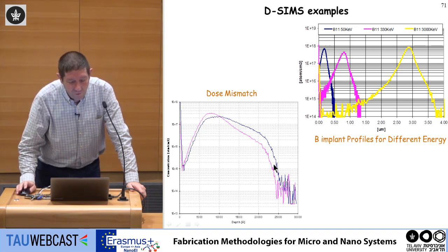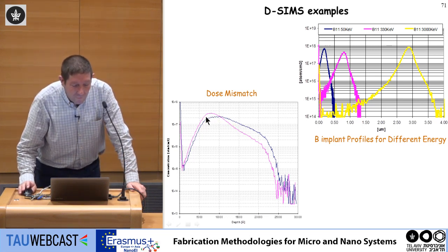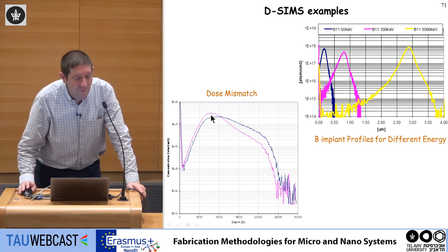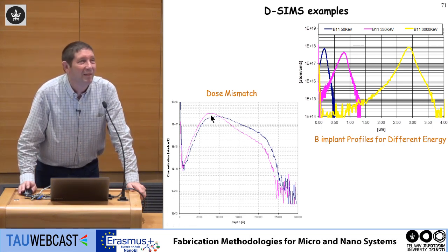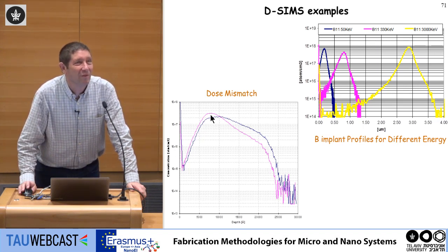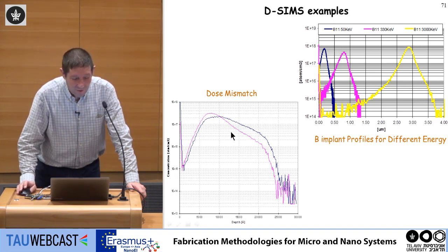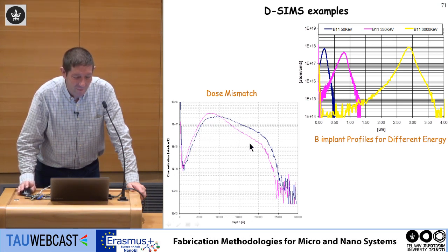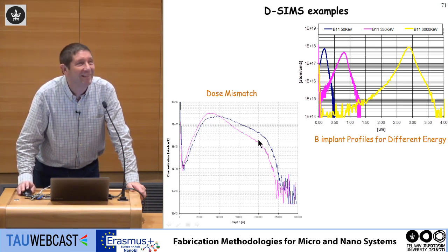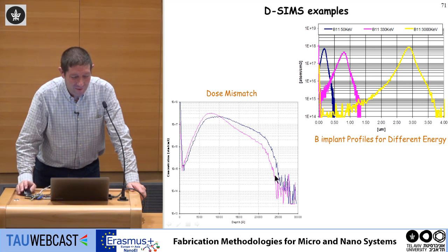So I can measure 10 to the 15, 10 to the 16, 10 to the 17 a few times. So this looks like a dose of 10 to the 17, typically threshold voltage correction. It's not source drain, or maybe well. I don't know what kind of doping. By the way, if you look here, you can see that you got one implant here and another implant. It's a kind of a complicated implant. It's not just one implant. It's a very tricky way to do this kind of profiling. I don't know what's happening here in the surface. Don't ask me. This is not my wafer.